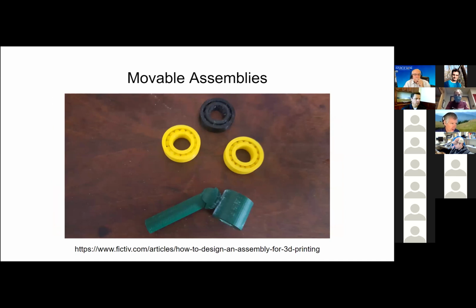The main reason we purchased a dual extrusion printer was to be able to print assemblies. As you know, the PVA dissolves away, and exploring further, I found a website that suggested allowing 2 layers into the design. 2 layers did not work on my printer. So I adjusted the slicer to its thinnest layer thickness, which was 0.15 millimeters, and allowed for 3 layers, which ends up being 0.45 millimeters, and then it became successful.